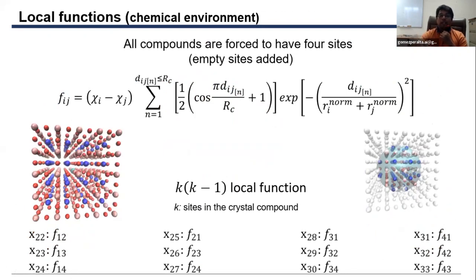The way that we model this chemical environment is with local functions that have a Gaussian profile, as shown in the formula. Those neighbor atoms closer to the central atom have a larger contribution to the value of the local function. And this interaction between the central atom and the neighbor atom is modulated by the sum of the atomic radii of the involved atoms. In a collection of compounds with up to 4 Wyckoff sites, there are 12 local functions or 12 features describing 12 chemical environments. And in a collection with up to 6 Wyckoff sites, you can obtain with this formula 30 local functions.